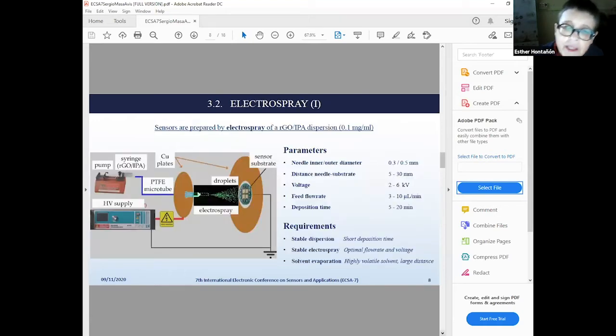This is a layout of the experimental setup we have used for electrospraying the RGO dispersions. We put a few milliliters of this RGO dispersion in the syringe, and with the help of a pump it is fed through a capillary tube to the tip of a metallic needle at a constant rate, and a high voltage is applied on the metallic needle, and in front of that we put the electrode on which the sensor substrate is supported, at a given distance from the needle tip.